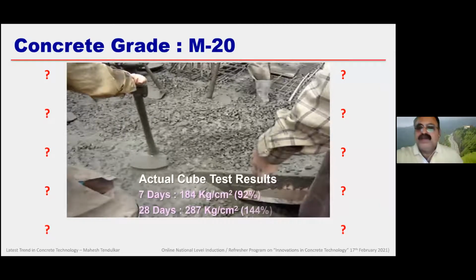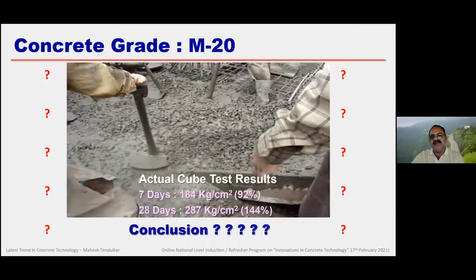So without doing any adjustment, we took these cubes for testing the concrete. And you will be surprised to know the strength of concrete was 90% in 7 days, and at 28 days it was about 280 kg, so more than 25 MPa strength. So we get confused. What can we conclude from this, whether such kind of workmanship is good or bad? Still we say it is bad, but still it is giving results.